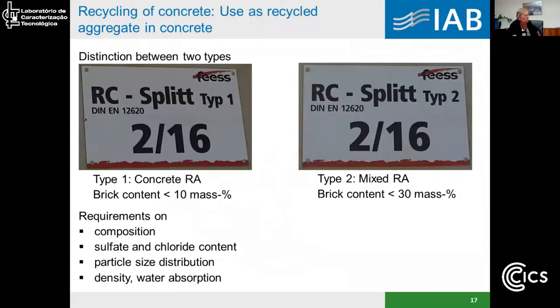We can distinguish between two types of recycled aggregates. First is so-called concrete recycled aggregates. There, the brick content is limited to 10 mass percent. Then the second type is mixed recycled aggregate. The brick content must be lower than 30 mass percent. And in both cases, it is not allowed to use the particles with diameters lower than 2 millimeters. Therefore, here is written 2 to 16. That means that is the particle size.